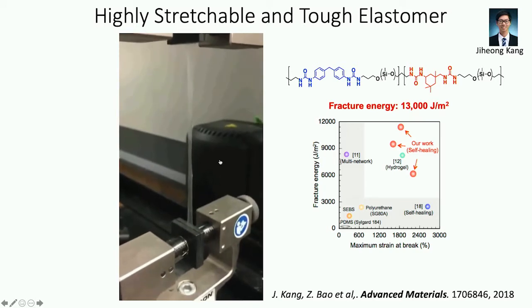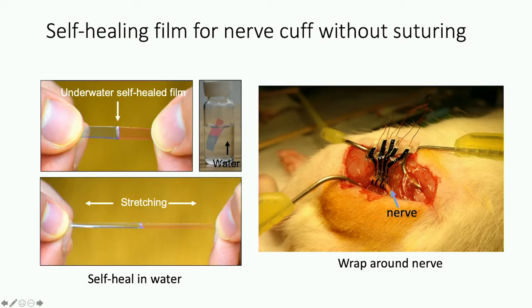So with these kinds of self-healable materials, we started to explore the potential places where we can use them. For example, this self-healing material can heal even in the presence of water. Even though it has hydrogen bonding, the bonding is strong enough that it can actually heal in water. This is currently how we make these nerve cuffs: the nerve cuff contains conductive material and the substrate, then we just wrap it around the nerve and the hydrogen bonding will form at the interface and allow us to form an intimate contact between the conductive stimulator as well as the nerve.